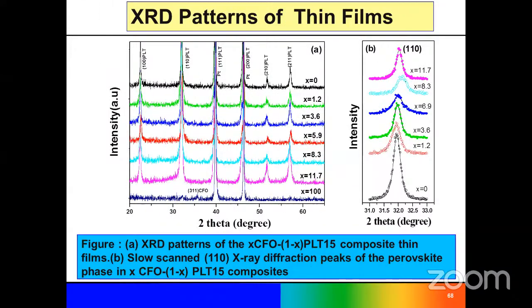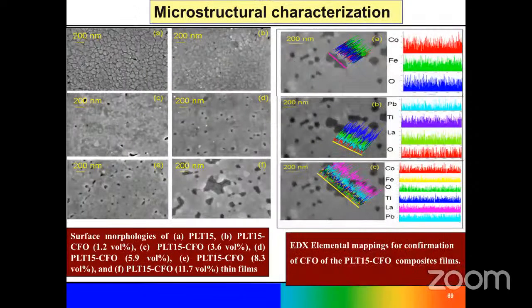If you see the structural morphology of this cobalt ferrite CoFe2O4 doped PLT15 matrix, there is an interesting point: after a certain percentage of cobalt or CFO, there is a shifting of the peak. That means there is a diffusion of cobalt inside the PLT15 matrix. It gives some very important phenomena in multiferroic thin films. The elemental analysis confirmed that cobalt, iron, oxygen and PLT, lanthanum, lead, titanium are all present in the matrix.